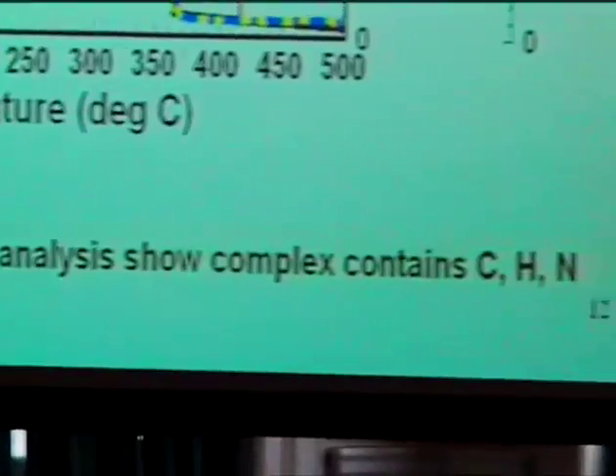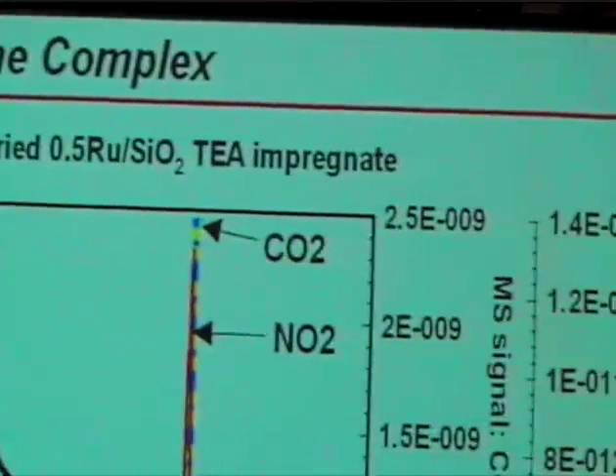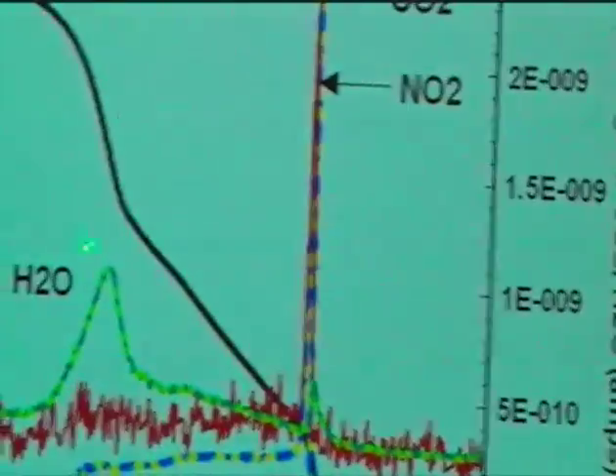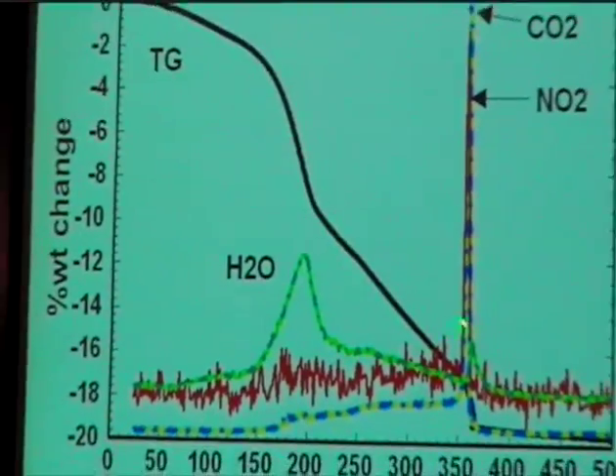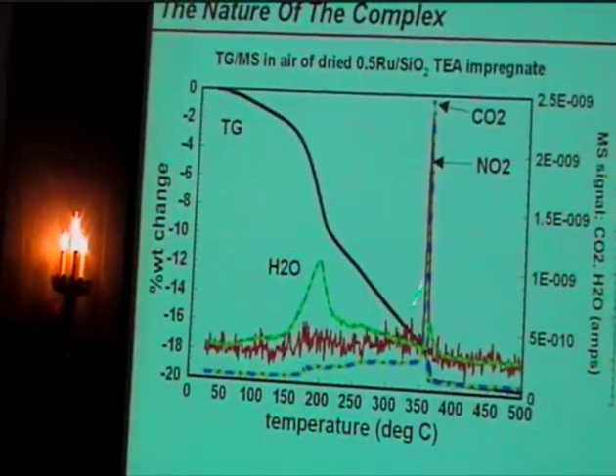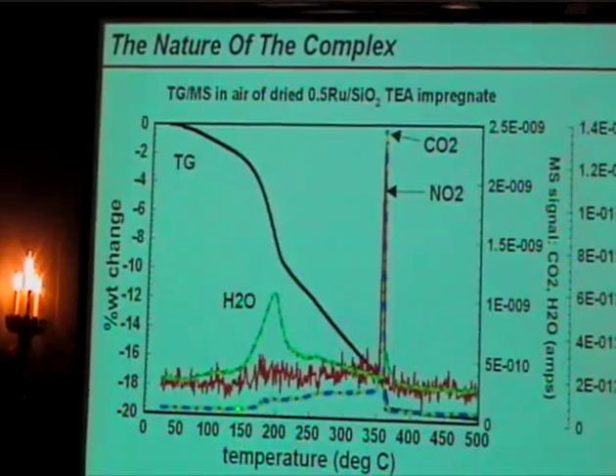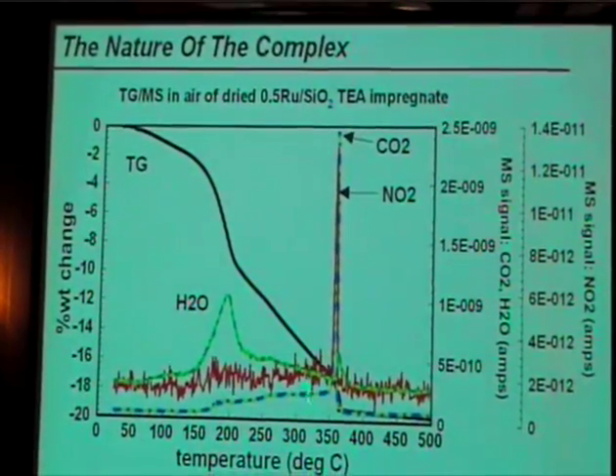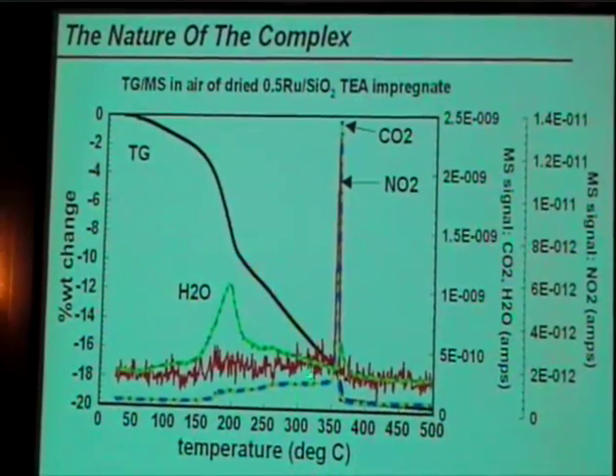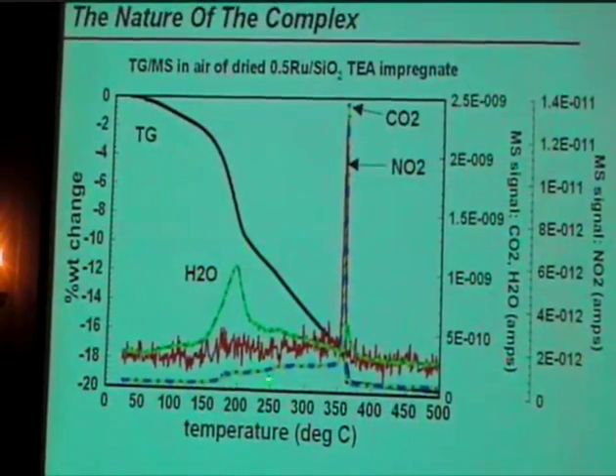So what is this complex? I'll just try to spend a few minutes, have time for the rest of this stuff, to talk about this. So we did a little bit of characterization. You go back and look at the TGA and now look at the TG mass spec analysis. And what you see, this green trace is water that's coming off as you're heating up. The CO2 is this blue and yellow line. You can see at that low temperature where we had those exotherms, we are losing some carbon. There is an oxidation going on there.